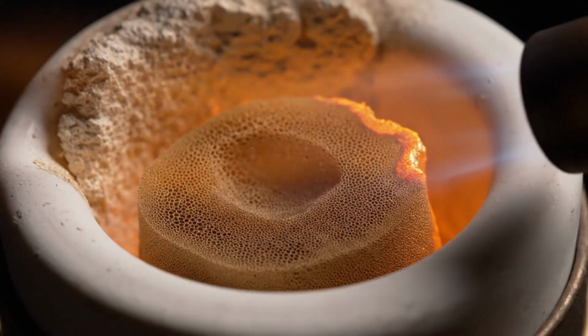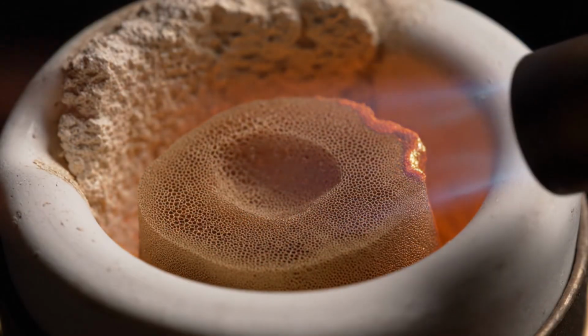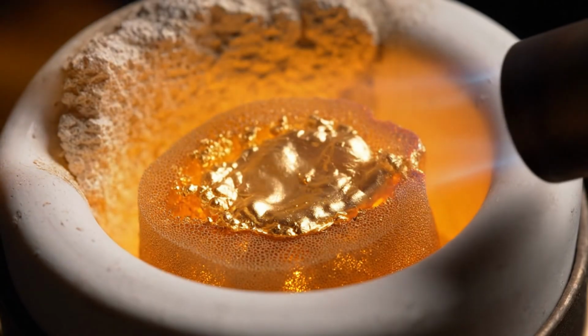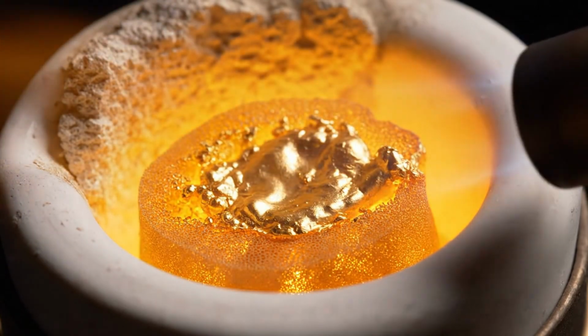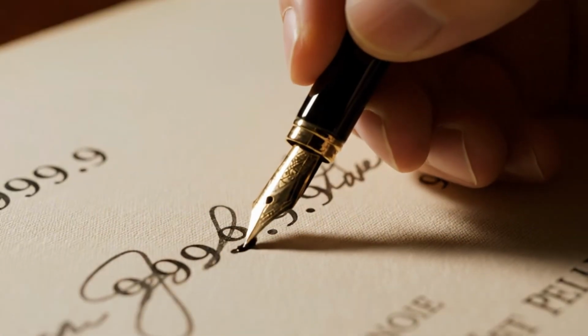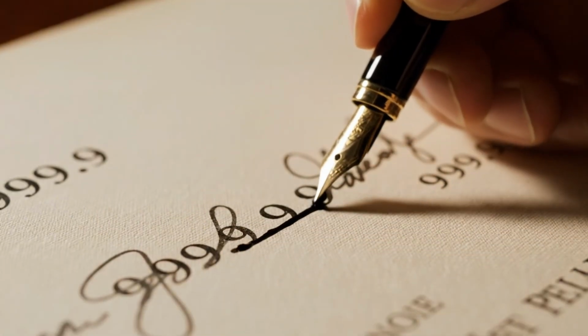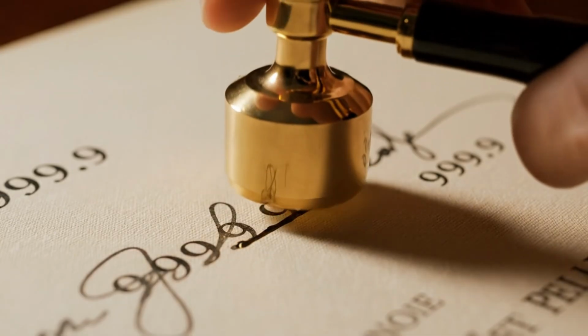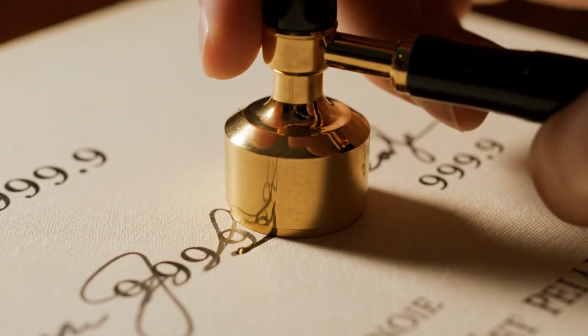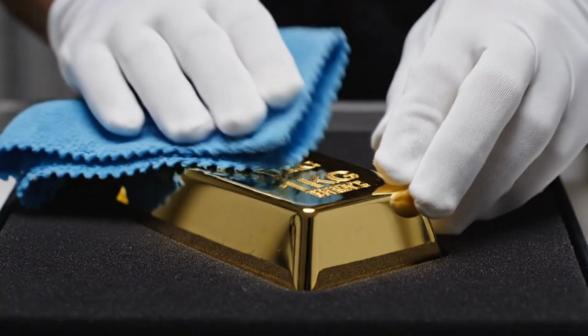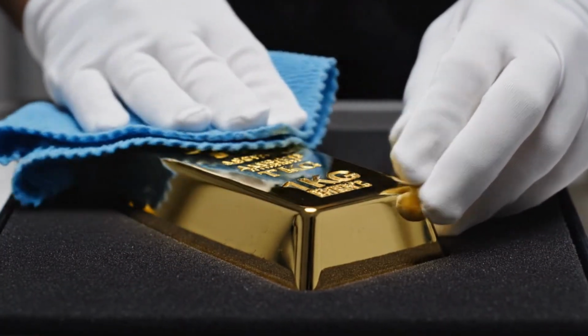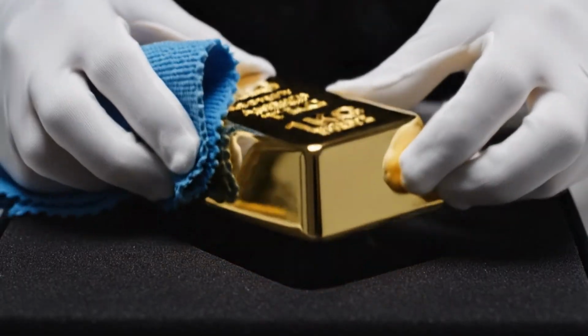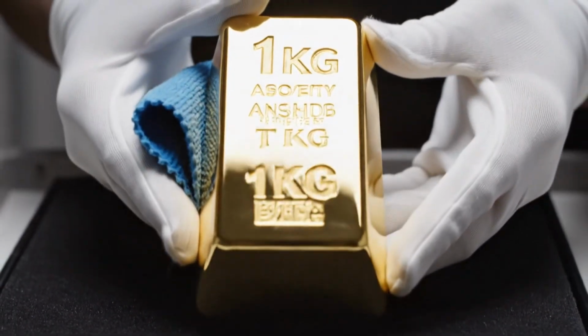We anneal this gold sponge, bringing back its metallic luster before weighing it once more to calculate the exact percentage of purity in the bar. The calculation confirms the four-nines standard, allowing the master assayer to sign the certificate of authenticity that will accompany this specific bar forever. Back on the floor, the approved bar is carefully handled with lint-free cloth, ensuring no dust settles on the mirror finish before final packaging.